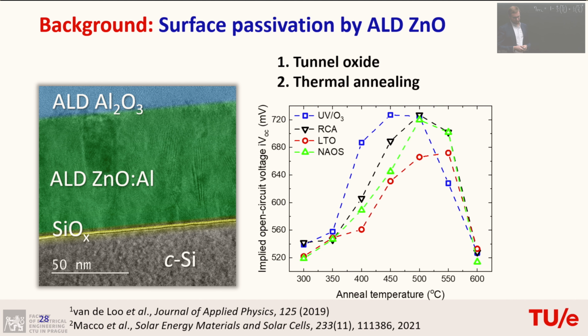So what else do we need then? We need some heat. So also, like in the previous case, you need to anneal your sample to make sure that hydrogen is probably able to move and reach your silicon interface. So here, for different kinds of interfacial oxides, don't worry too much about all the data points, but you see that if you increase the annealing temperature, you eventually improve this implied VOC, meaning you can reach high values.